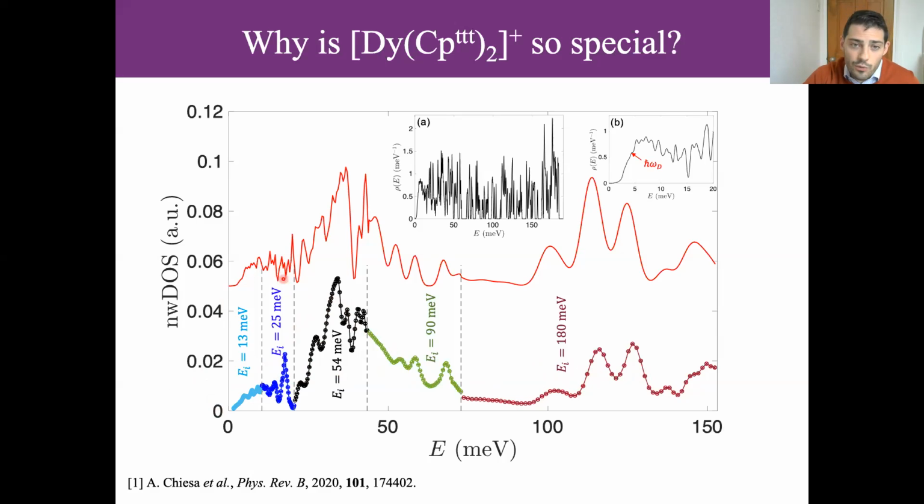And so then this here in red is the DFT calculation, a periodic DFT crystal calculation of the phonon modes, where we've used the same experimental broadenings that we have in the experiment. And we see a pretty good agreement, I would say. You know, I think that's pretty passable for modeling the phonon modes.